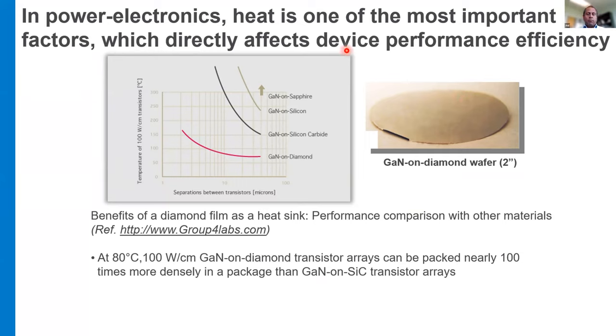that by integrating diamond, physically bonding the diamond on the gallium nitride, you can reduce the temperature of the device. So in this case, it shows that 80 degrees centigrade, 100 watts per centimeter GaN on diamond can be packed nearly 100 times more densely than the GaN on silicon carbide. Of course, this work was done by the Group4 Labs some time back. Now it's been acquired by another company.